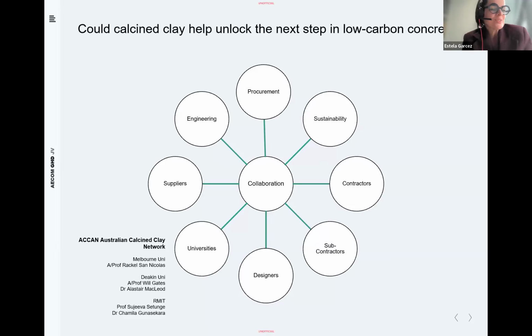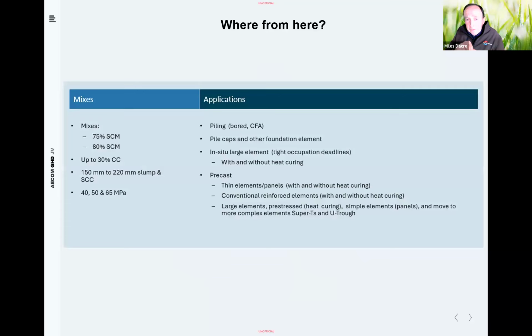Anything to add, Myers? Yeah, might go back to the previous slide, Estella, and just want to focus in on why we believe the approach is we think we could push calcined clay percentages up higher and redesign some fairly novel mixes around it. But the thinking is, if we're going to get the maximum GWP reduction in the shortest possible time, is to focus on this idea of we've got approved and proven mixes of 75% slag and combination of slag and fly ash. The clay will replace fly ash.